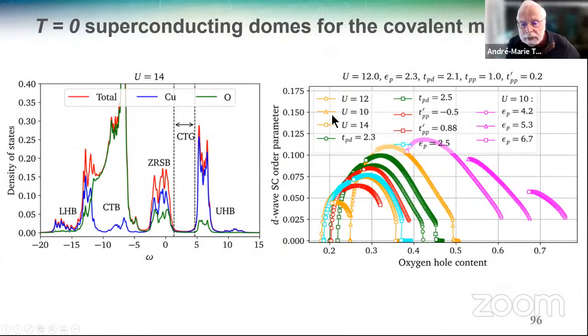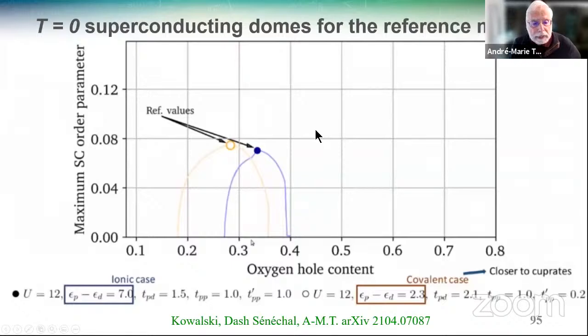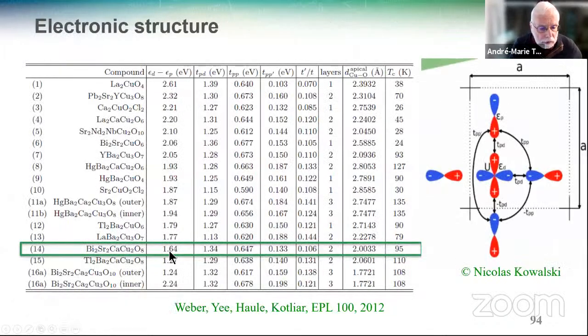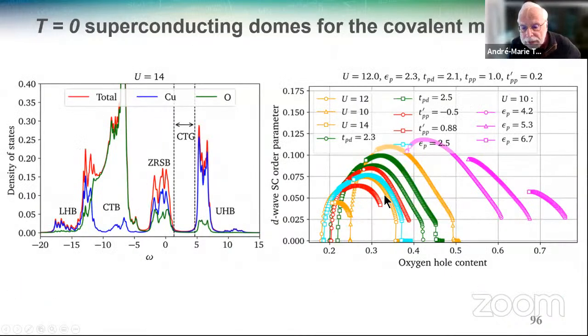Now the point is that I can mimic the fact that I change the values of the parameters within that range that I showed you here, the epsilon p minus epsilon d for the real values. And you can see that the domes indeed go to larger optimal doping when they have a larger oxygen hole content. Well, that's wrong here. I increase the oxygen hole content and it goes down in this purple region. Why is that? Well, in this purple region, the charge transfer gap closes. So the charge transfer gap is important.